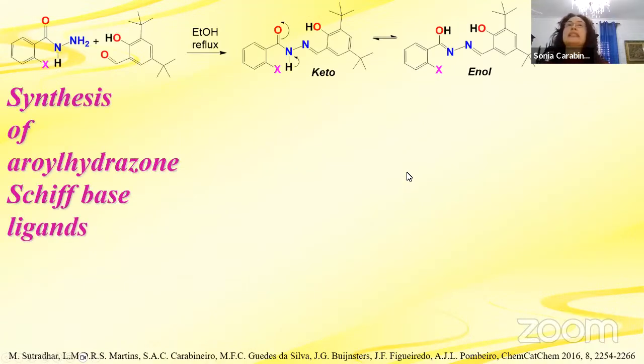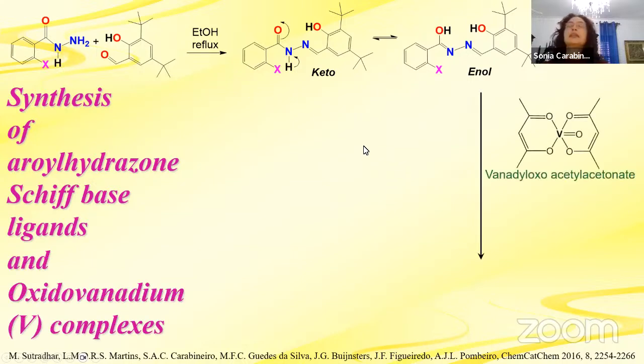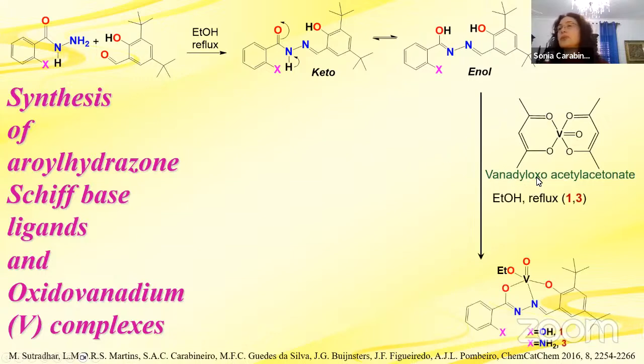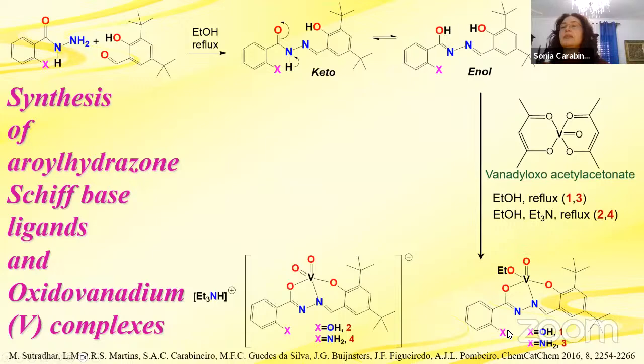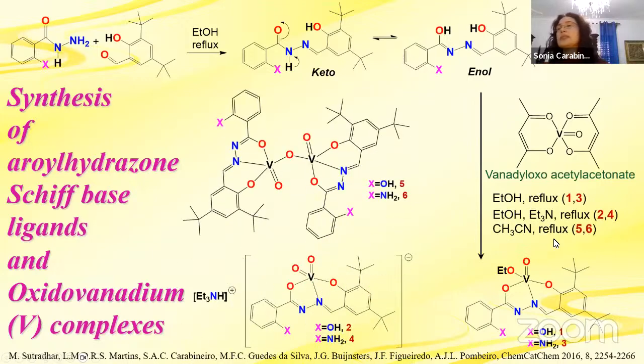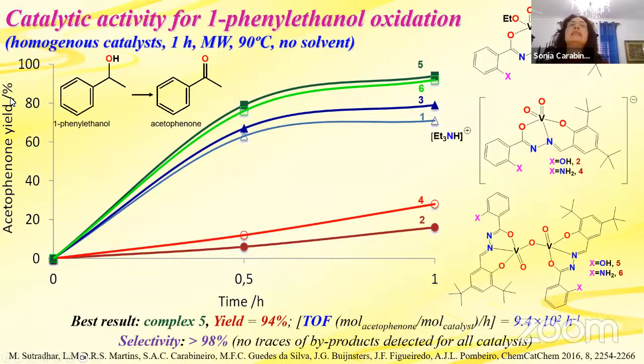And we also tested other vanadium complexes. So these Schiff-base ligands that were tested, that were synthesized this way. I'm not going to go into much detail because of limited time. So they were produced by reflux with this vanadium precursor. And here we obtain these complexes, these and these, according to the different conditions used for synthesis. So we obtain this type of vanadium complexes. And the catalytic activity for 1-phenylethanol oxidation was tested. So this is the homogeneous catalyst, and the best result was obtained with this complex 5, for a yield of 94%, very good selectivity as expected.